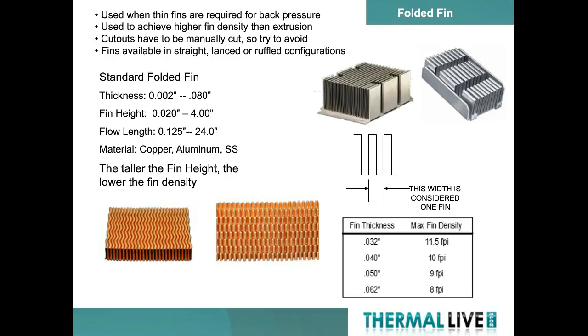One of the downsides of a folded fin is because of the thickness of the fin, they're extremely hard to machine after the fact. So if you want holes or cutouts or other features, that can be problematic. Typically, those are wire EDM'd into the part before it's actually bonded to the assembly. Some customers actually prefer to use just smaller sections of fins and just gang them up on a part rather than go through the expense of wire EDMing out the individual profile.